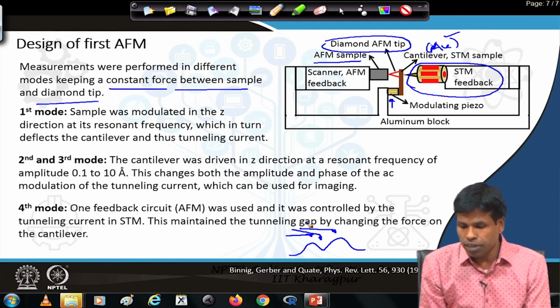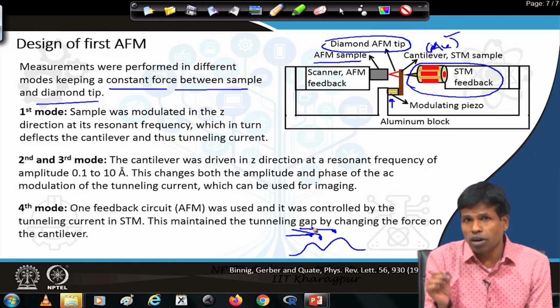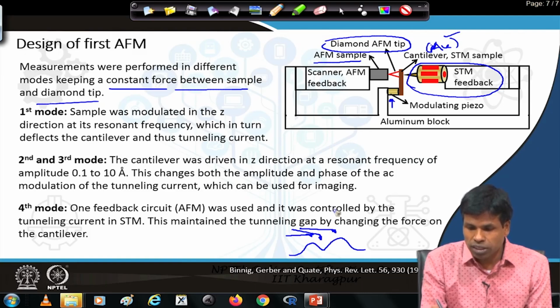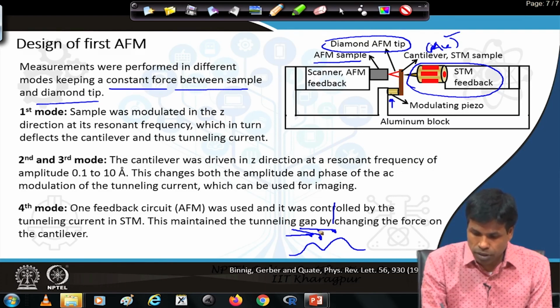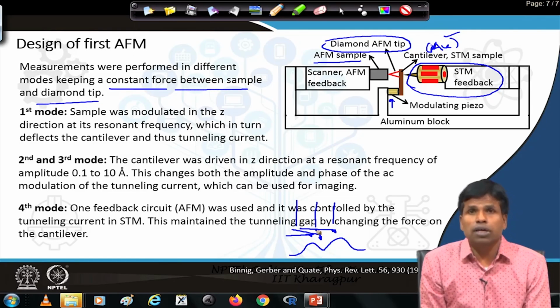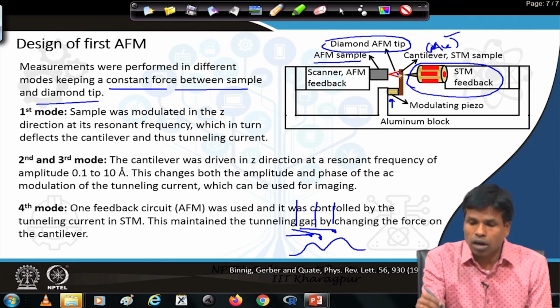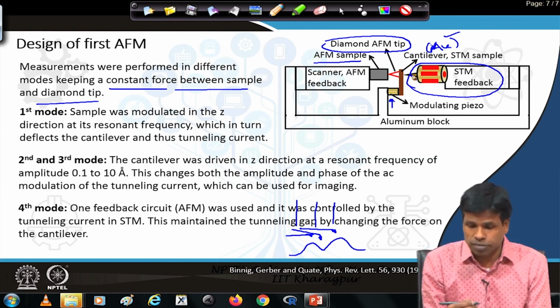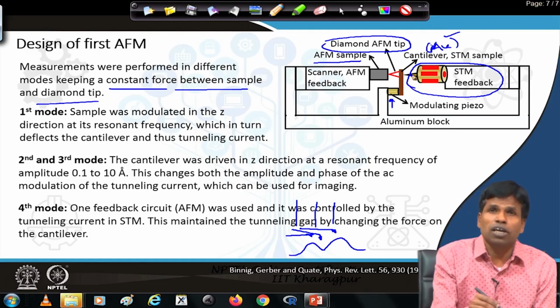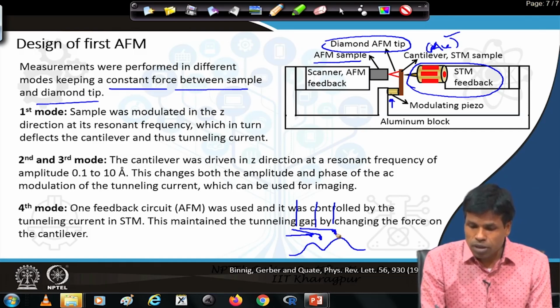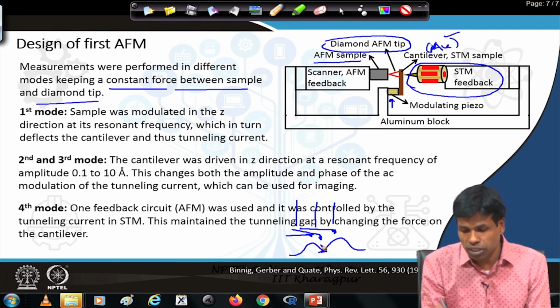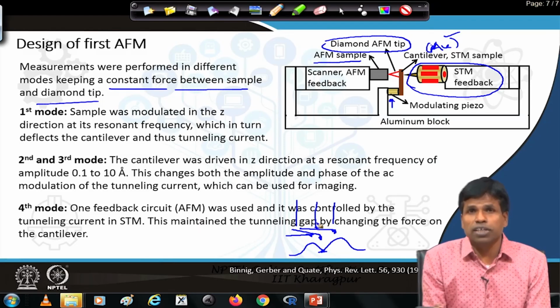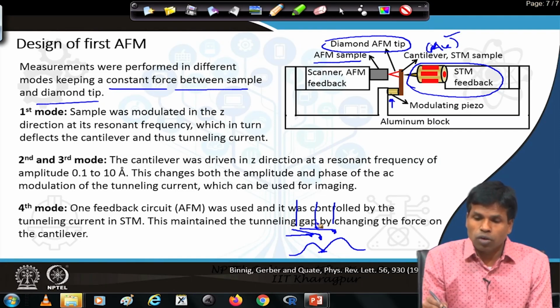Constant force will only occur when there is the same distance between the tip and sample, and therefore the cantilever has to bend downwards or upward. When the cantilever bends, the distance between the STM tip above the cantilever and the cantilever will be either far away or close. As the gap between the STM tip and cantilever changes, the tunneling current changes. That tunneling current was utilized to create the images. To measure constant force, the tip has to come down when the sample position is downward, and at those places the tunneling current will decrease. So, using that tunneling current, one can construct an image.